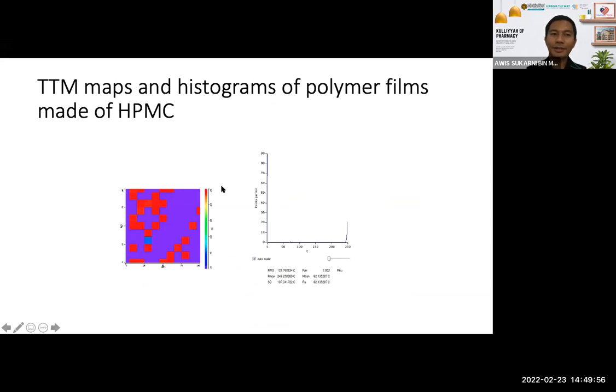So because of that, we start to prepare a film, because the film has a smooth surface. In theory, if you prepare a film, then you should get a uniform result based on the TTM. So when we run the TTM on the HPMC film, we noticed that we still found a few different temperatures here. This one is purple, the rest is red, and then there is an outlier here, blue color.